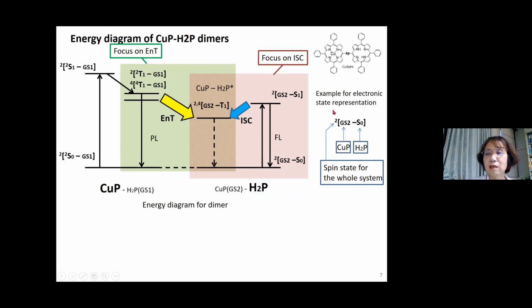before that, I have to explain how to describe the excited state. We should describe both the state and the total spin state of the whole system. So now, copper porphyrin and free base porphyrin are connected, and here we see mainly copper porphyrin. If we excite copper porphyrin from the excited singlet state, this means the singlet doublet state, it undergoes intersystem crossing, and we yield a triplet doublet and a triplet quartet state. In that case, the free base porphyrin is in the ground state, and then energy transfer occurs from the copper porphyrin excited state to the free base porphyrin.